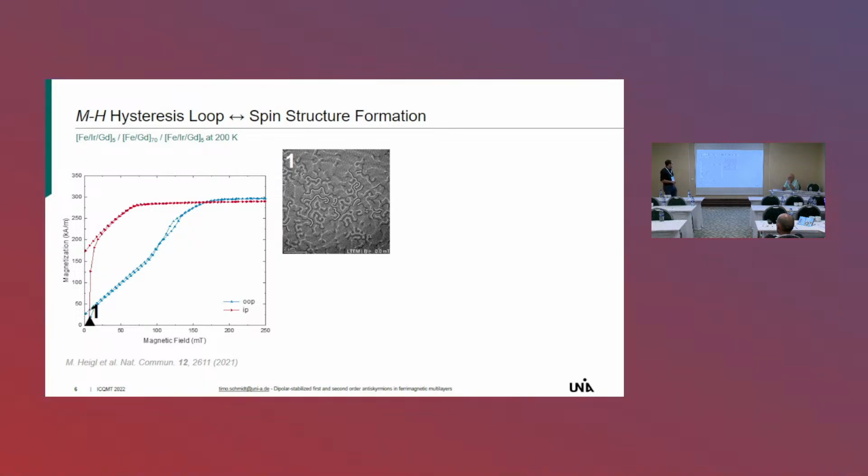And so that is that. Another thing you often see in Skyrmion samples is this small opening in the out-of-plane hysteresis loop, which comes from the fact that the nucleation and the annihilation of Skyrmions is an irreversible magnetization process. So if you go from zero field up to saturation, you get another path than if you go down. So let's go that way.